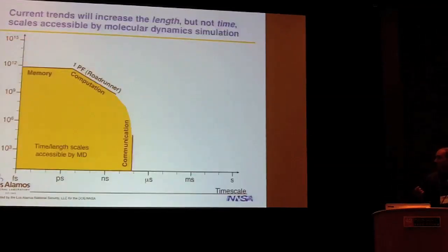If you look at what we can do on current petascale machines, we're starting out down at the resolution of the system at the 1 atom length scale. And to have a stable time-stepping algorithm, we need to resolve the atomic vibrations of that atom, which requires a time step on the order of femtoseconds. So starting out down here, on a typical, say, Roadrunner or Jaguar or other systems, if we just fit all the atoms into memory that we can with, say, 100 bytes per atom, that puts us at roughly 1 trillion atoms.